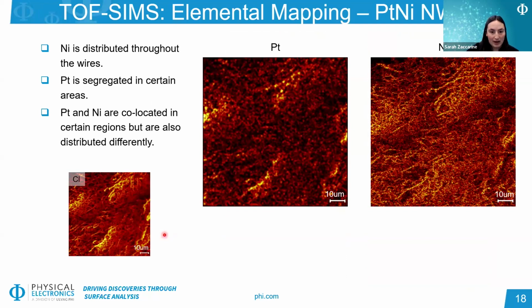So we also were able to map the platinum and nickel distribution in these wires. The platinum signal is quite low compared to the nickel. We see the nickel is really present throughout on all of these individual wires. Again, it's a bulk nickel nanowire template, and the platinum is really more of a thin surface layer, but the platinum also has a slightly lower ion yield, so that is leading to the lower signal.